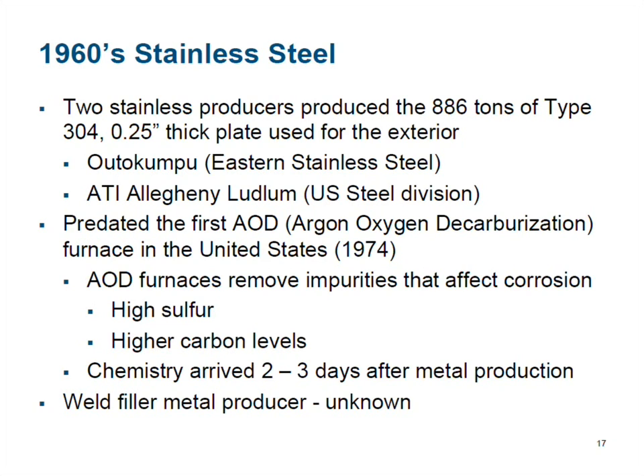The first AOD, argon oxygen decarburization furnace, in the United States was not installed until 1974. AODs allow removal of a lot of impurities. It was not possible to make low carbon stainless steel consistently until those were introduced. So we had to assume the stainless steel on the arch was not going to be low carbon, which introduces the possibility of things like weld sensitization. It also meant it was likely to be high sulfur, and high sulfur also introduces some potential corrosion issues.